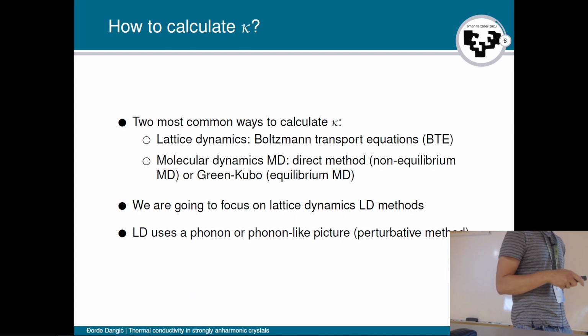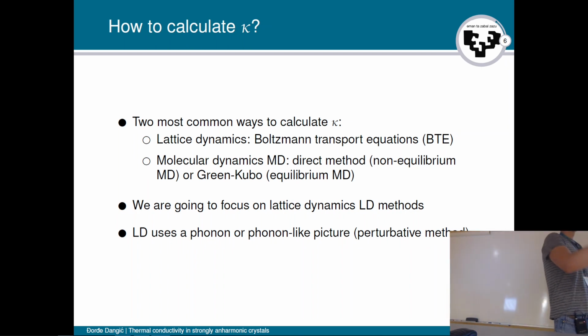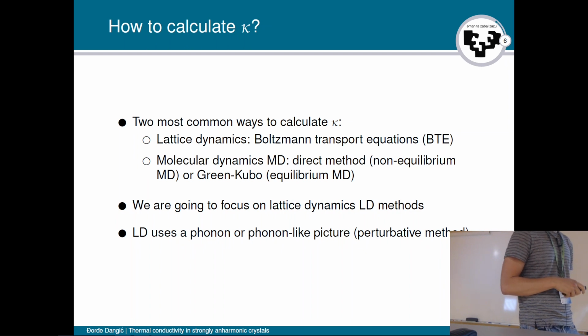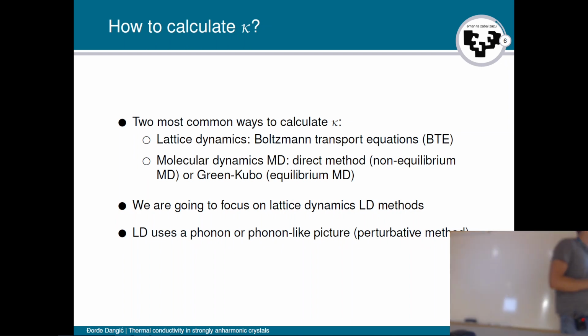One is the direct method, which is basically just reproducing the experiment in the molecular dynamics simulation. So you make a very long simulation cell, then you take heat from one side or from the edges of your simulation cell and put it inside in the middle, which basically creates a heat current from the ends to the middle, and then you know the heat current, and that heat current will generate a thermal gradient, and then you can calculate the lattice thermal conductivity just as you would do it in the experiment. And the second method is using the Green-Kubo relations and calculating lattice thermal conductivity from the fluctuations of the heat current in the equilibrium MD.